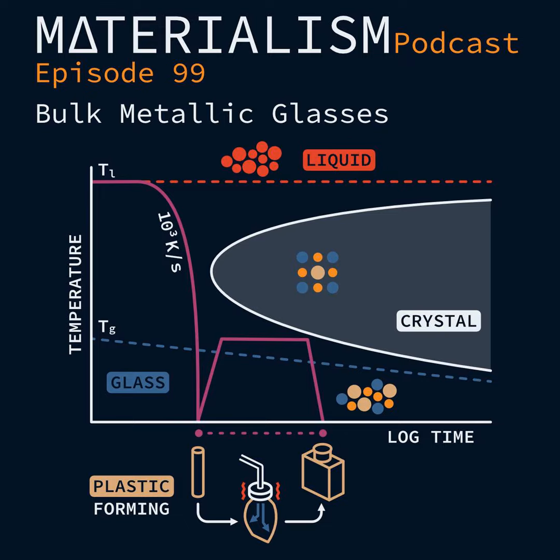They were also easier to make, even with lower rates. So you could make macroscopic samples and mechanically characterize them. People discovered they have very unusual mechanical properties, like really high strength and really high elastic limits. Exactly. The major difference, and people often are surprised: if you take a titanium-based metallic glass or a piece of titanium or Ti-6-4, they look essentially the same. But if you put them under a microscope, your eyes pop out. Or if you mechanically characterize them, they are very, very different.